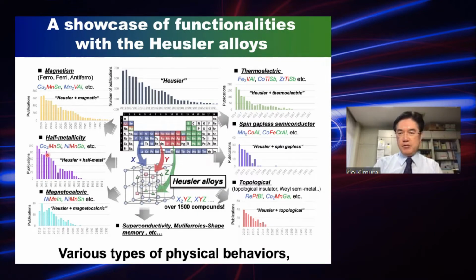Also, good thermoelectricity is realized for iron-based Heusler alloys. And recently, the spin gapless semiconductor was predicted for Mn2CoAl and related alloys. We can also see some topological aspects in several Heusler-based alloys. Recently, substantial thermoelectric and Nernst effect was found in the Co2MnGa alloy, which may be due to some Berry curvature in the band structure.